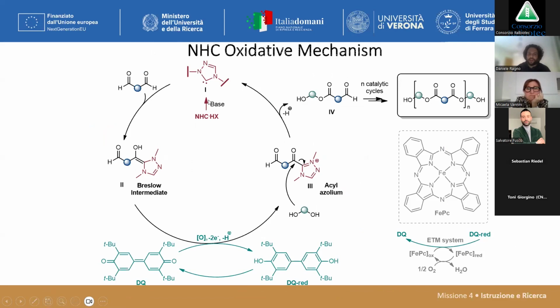Just a few words on the chemistry. I will not be so boring, just to show how it works, because it's something that is shared for all the works. We get this N-heterocyclic carbene, it's very cheap and easy to generate with a proper base. Then this carbon-centered Lewis base can attack an electrophilic dialdehyde, giving the Breslow intermediate. This Breslow intermediate can be oxidized with a proper oxidant, a very cheap and totally recyclable diquinone, the so-called Kharasch oxidant. And then you end up with an electrophilic acylazolium that can be intercepted, in this case, with a diol, and then you end up with your product. And after several catalytic cycles, you observe the chain growth, and you end up with a polymer.